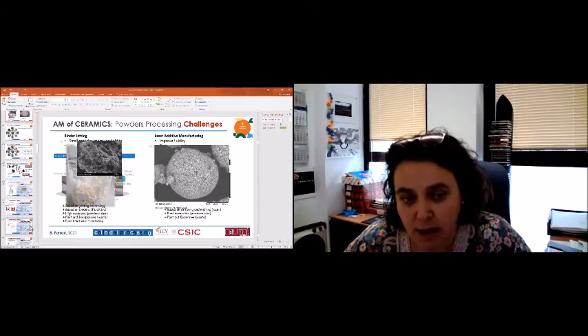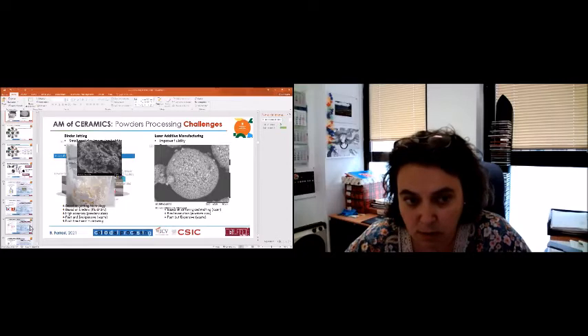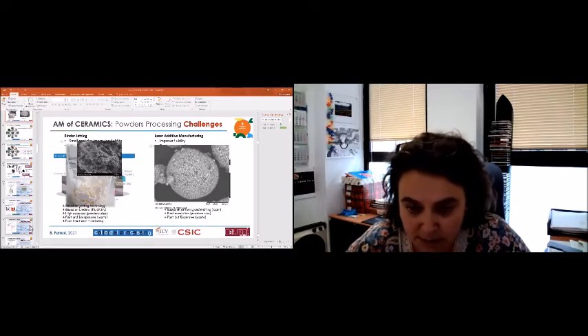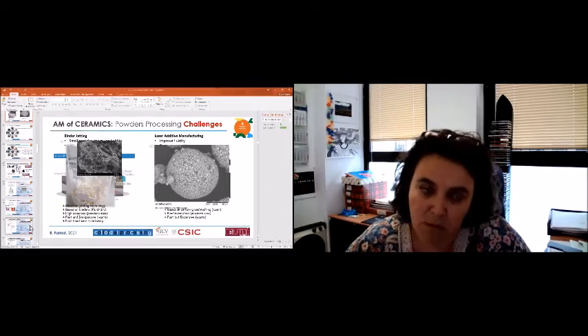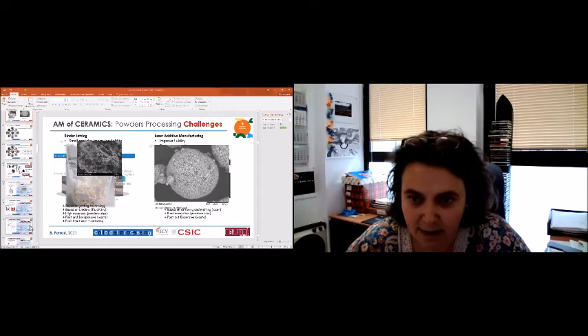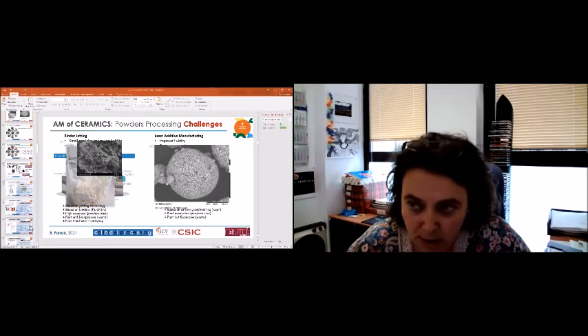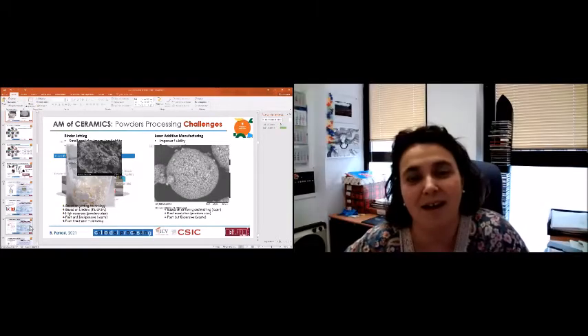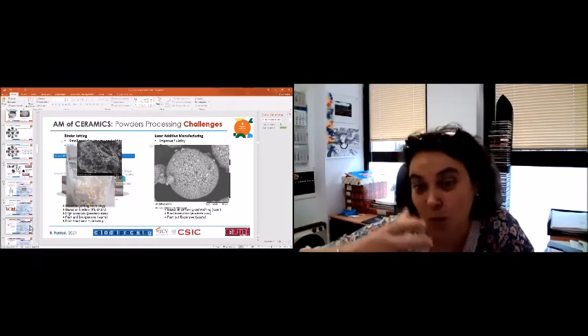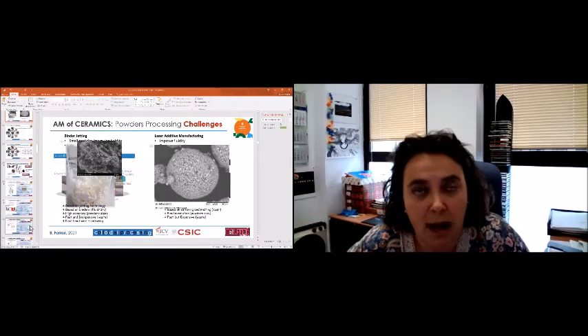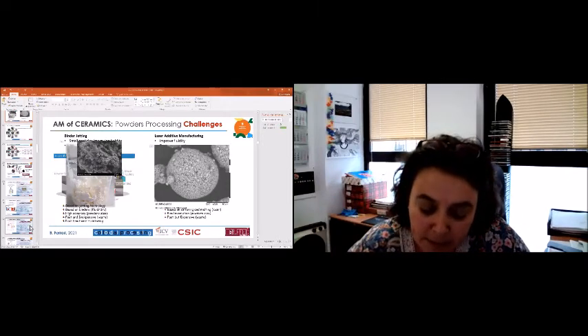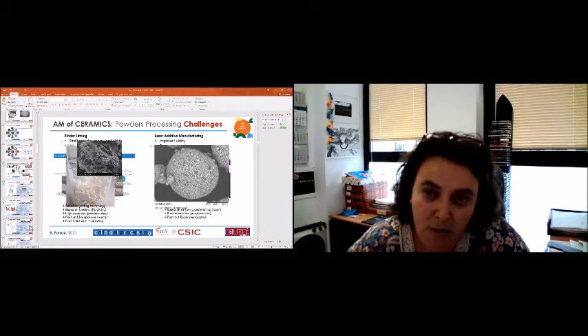But in powder metallurgy, we have some experience there, and fluidity is very important to fill the mold, right? You need to fill the mold before pressing, and fluidity in this case is really important. It's very important to have the apparent density and the tap density close, right? Even when you have pressing later. And here I agree with you that we are not pressing the piece at all, but the fluidity of the ceramic powder is really, really bad. Yes, we know that.